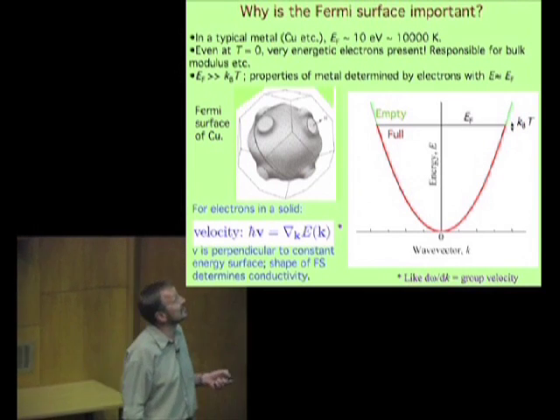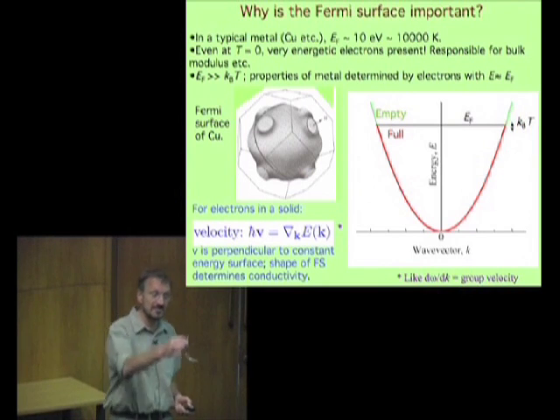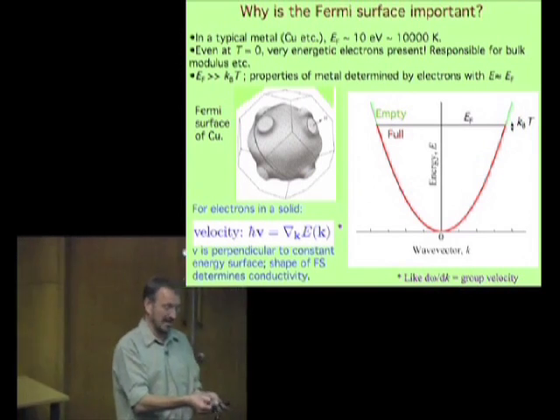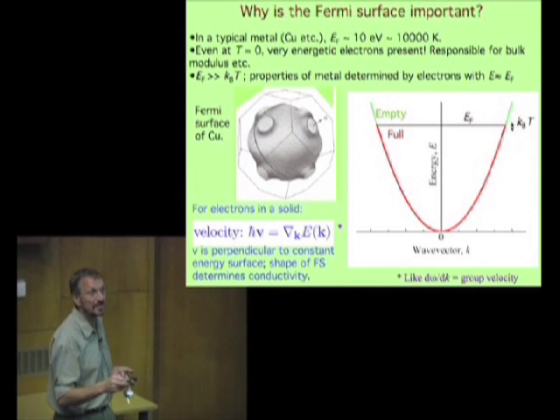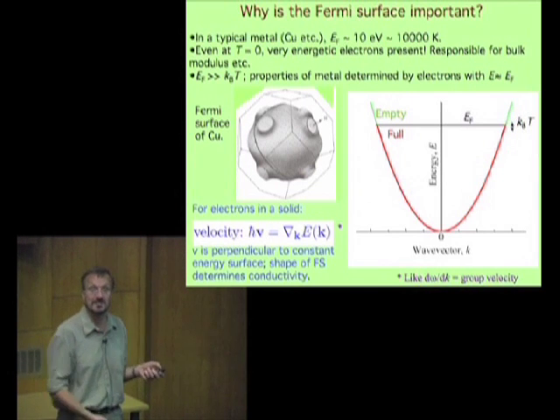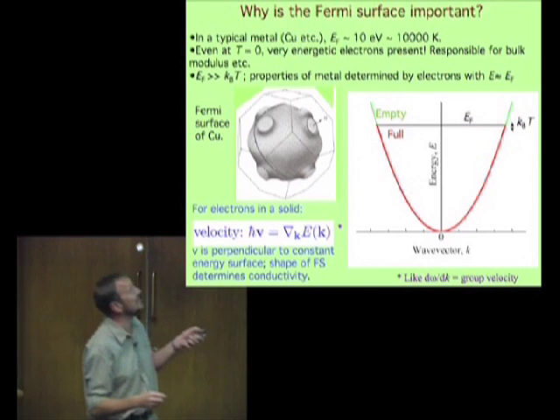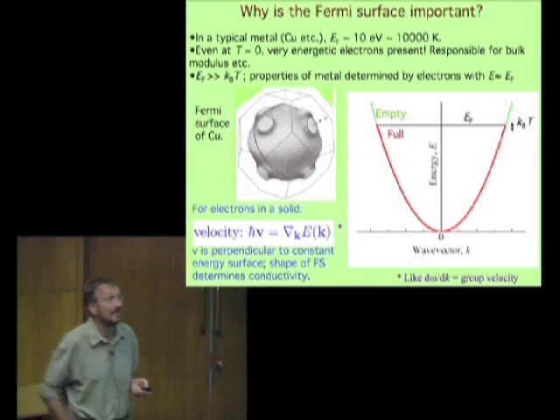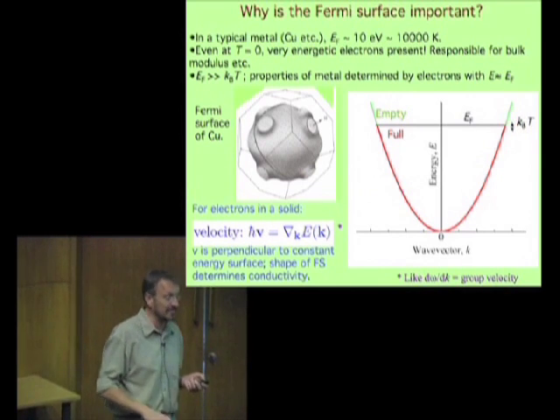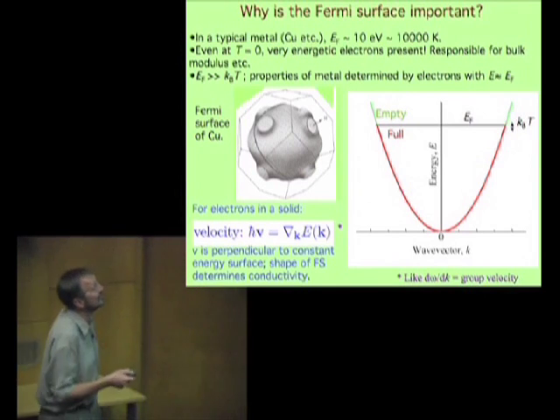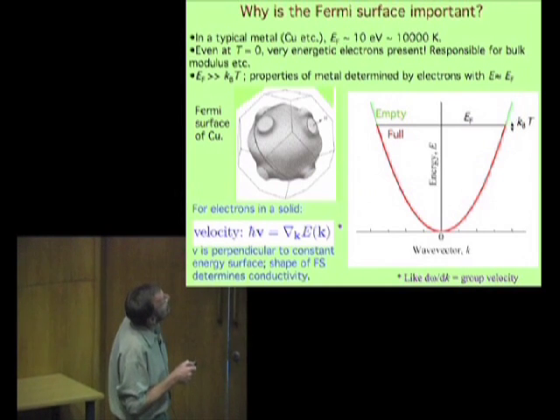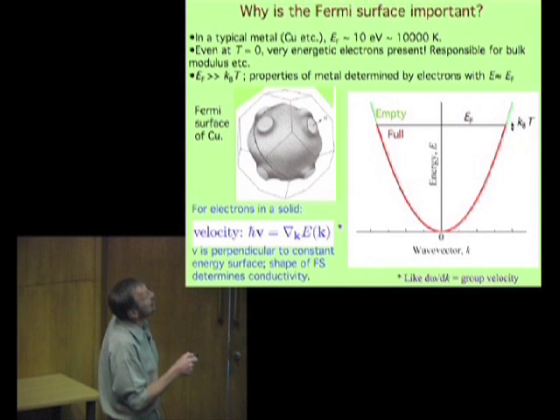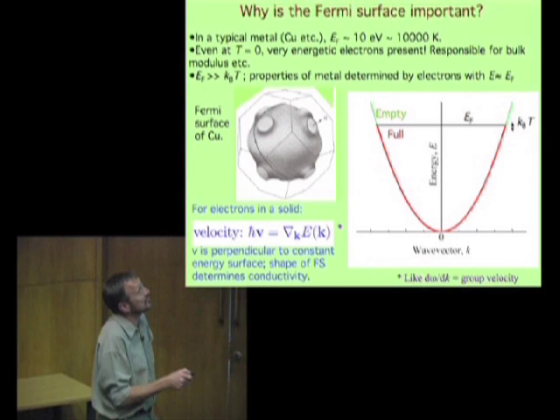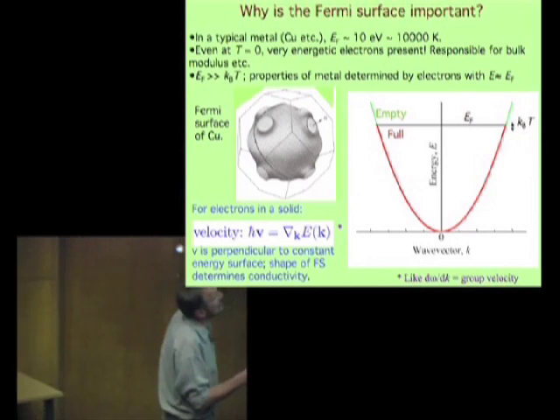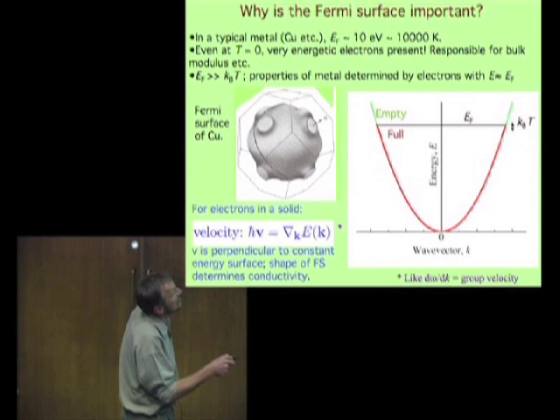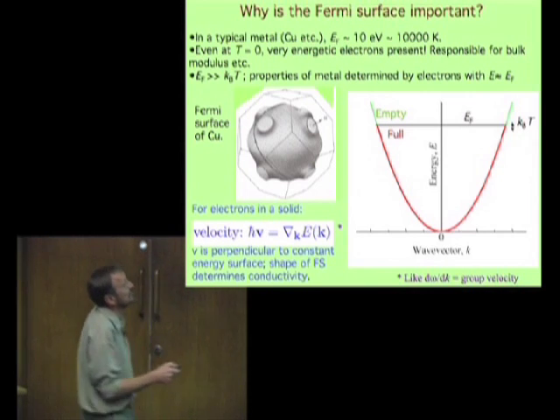So for a conventional metal like this, most of the properties can be understood by these electrons. For instance, if you take a set of keys and you try to squash a key with your bare fingers, the metal in the key is resisting this pressure. It's actually the electrons at the Fermi surface that are resisting this pressure. If you work out the bulk modulus of this gas of fermions, it accounts for most of the bulk modulus of the metal. So if electrons were not fermions, basically metals would be little pools of sludge lying on the floor with no rigidity or no bulk modulus. So now this Fermi energy is much greater than the temperature as well. So the properties of the metal are determined by electrons with energies approximately equal to the Fermi energy. The reason for that is that this energy is so much greater than the temperature, so thermal excitation can only populate and depopulate a tiny fraction of states either side of this.